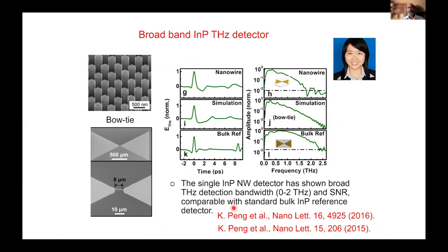Again, to cut a long story short, during her PhD, Kun Peng demonstrated gallium arsenide-based single nanowire terahertz detectors, and later on, indium phosphide-based single nanowire terahertz detectors. She used something called bow-tie antennas to create broadband detectors. And here are the simulated spectra, the nanowire measured ones, and also a bulk reference, showing that nanowire-based detectors are as good as the bulk ones, but much more compact.